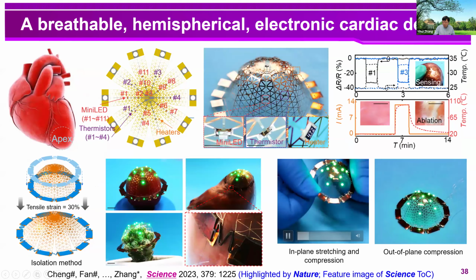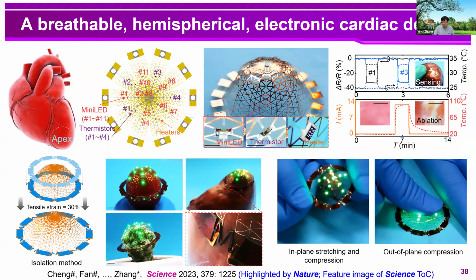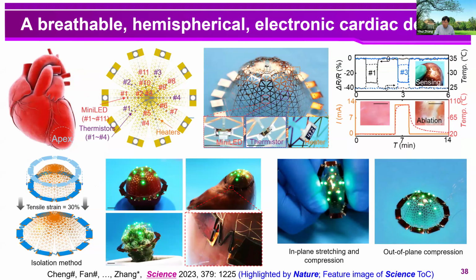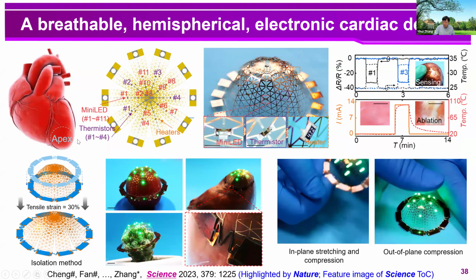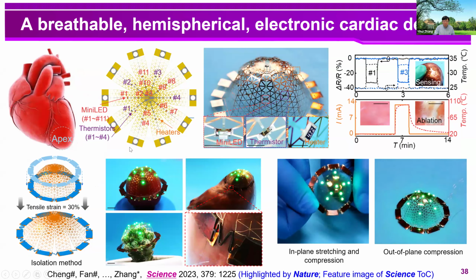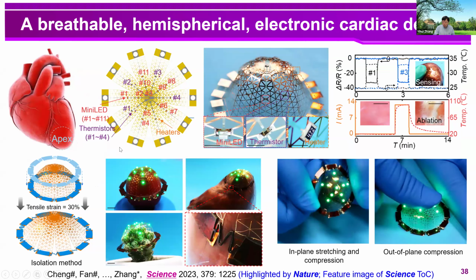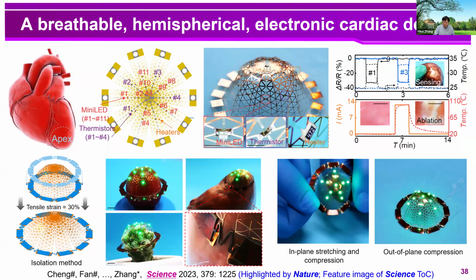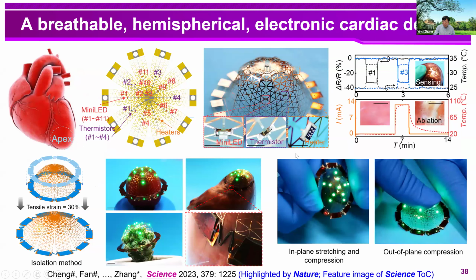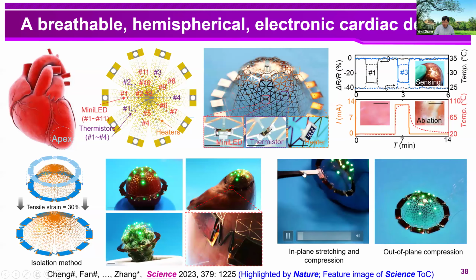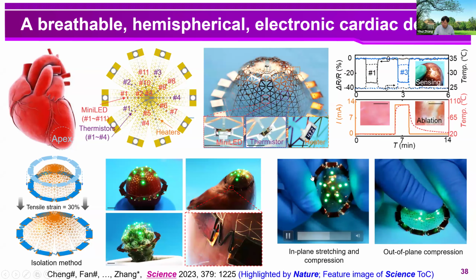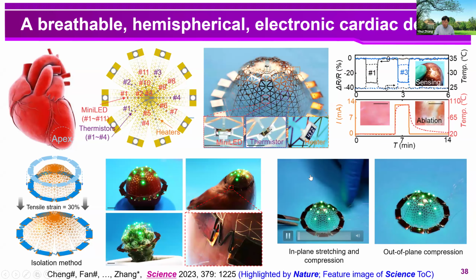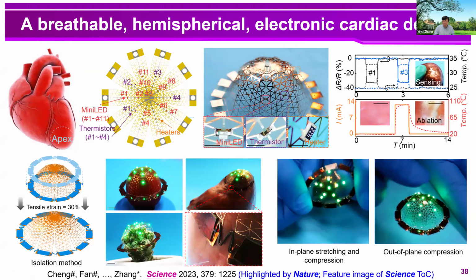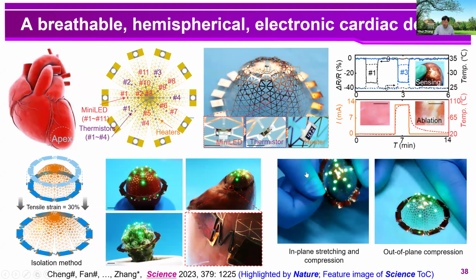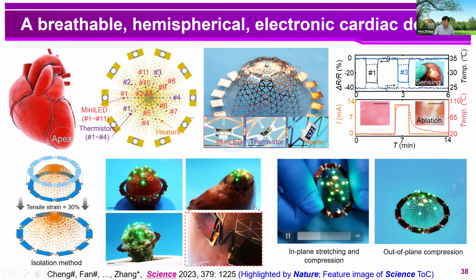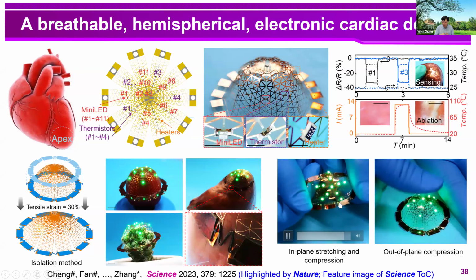Here is another example in terms of a breathable hemispherical electronic cardiac device. According to the geometric feature of the cardiac apex, we can design a 3D cardiac device with similar 3D geometry and a similar dimension to match the design target. As you can see here, this 3D cardiac device can adaptively wrap onto the curved surface to offer high signal-to-noise sensing of the temperature. It can also achieve localized thermal ablation by using the microheater. And because this device is very flexible, it does not induce large mechanical constraints during the heart contraction and expansion.